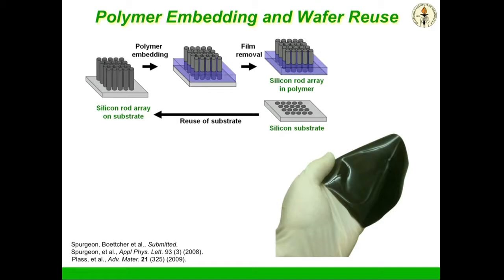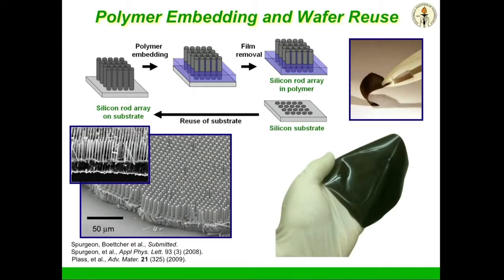And these little stubs of silicon are easily etched in a quick 30-second dunk in 1 molar potassium hydroxide. And that leaves behind the same holes that we started with, that then we electrodeposit more copper metal, that then we grow, and then we peel, and then we etch, and grow, and peel. And so this is a template, just like printing money with a template, that we use over and over again. And so we've shown that we can recycle that substrate, and by the time you've cycled it 10 times, its cost is negligible, and we can project at least 100 times.